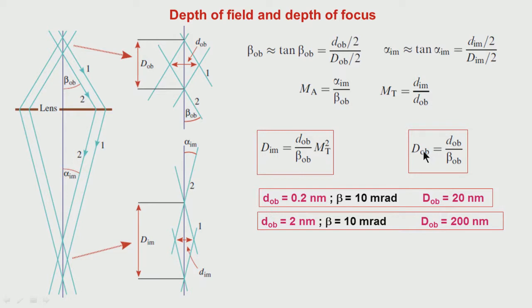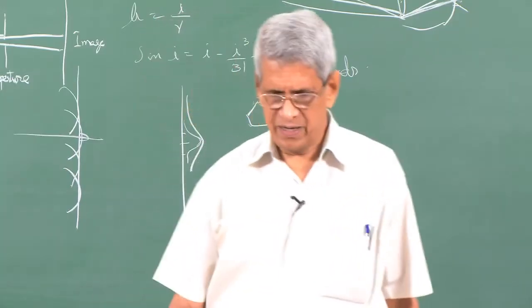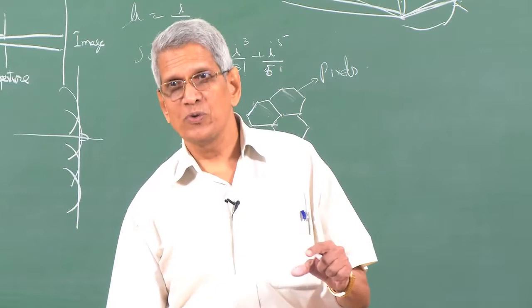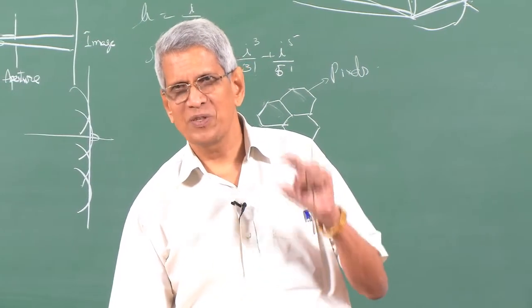Similarly, the depth of object, this distance where that object is in focus, is given by the resolution which we are looking for divided by the angle which that object subtends with the lens. If you do a simple calculation, suppose we say that this D object I put as 0.2 nanometer, because I want a resolution of 0.2 nanometer in that sample. Then if beta equals 10 milliradian, the D object turns out to be 20 nanometers. That means a sample of only 20 nanometer size we have to use if we want the full sample to be imaged very clearly.